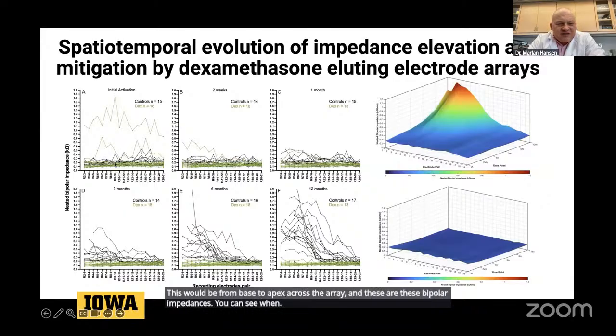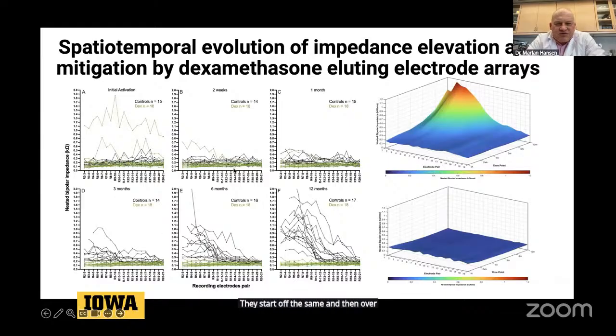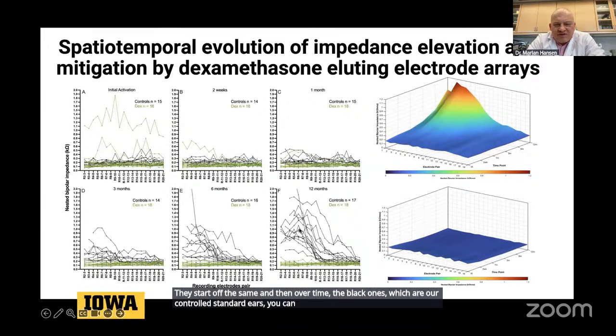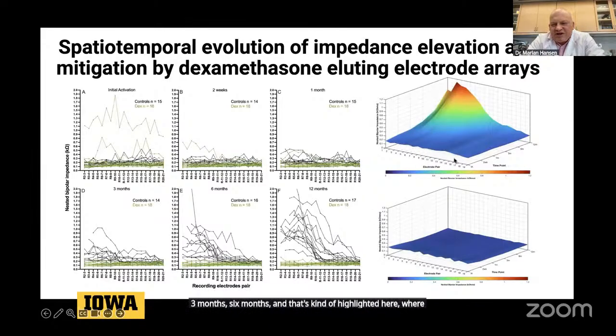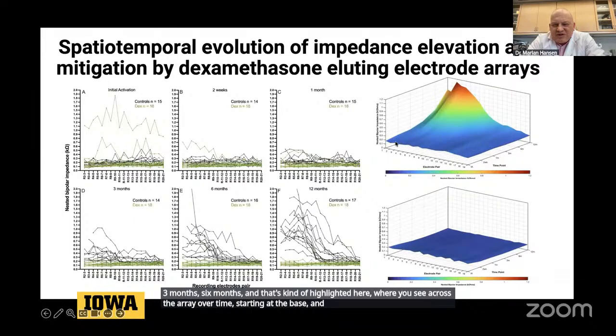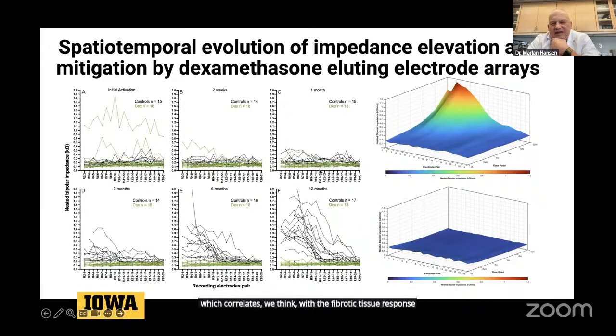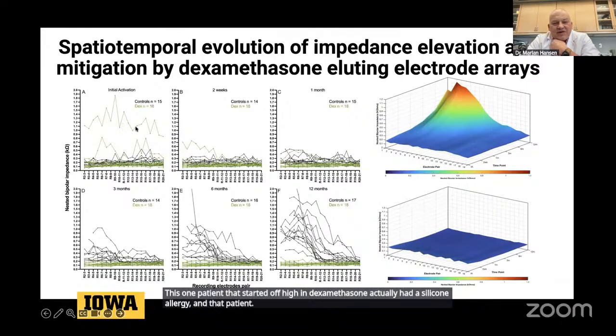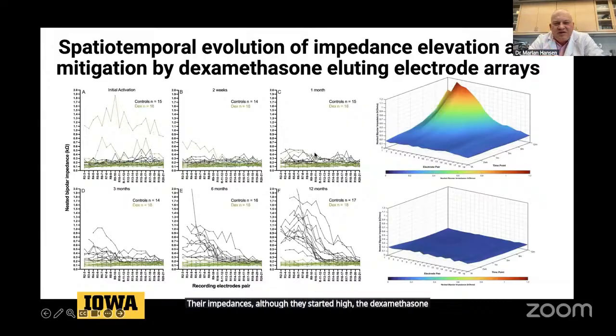You can see they start off the same, and then over time, the black ones, which are our control standard ears, show the growth of this tissue response. It starts in the base and then grows over time: initial activation, 1 month, 3 months, 6 months. That's highlighted here, where you see across the array over time, starting at the base and then moving, you get a dramatic rise in these bipolar impedances, which we think correlates with the fibrotic tissue response. The dexamethasone completely suppresses that, even out to a year. This one patient who started off high actually had a silicone allergy, and although their impedances started high, the dexamethasone suppressed those by 1 month or by 3 months.